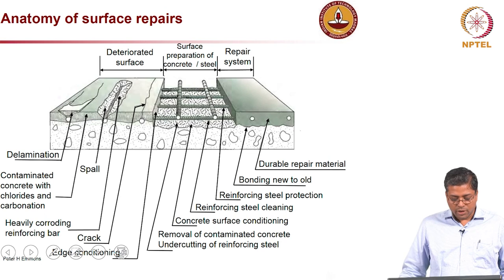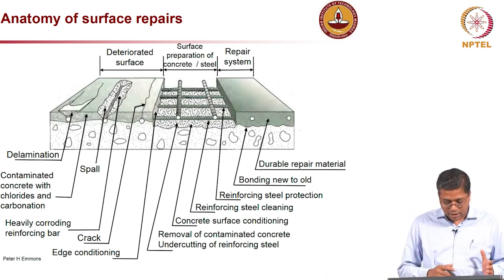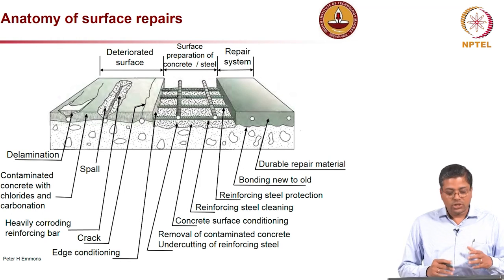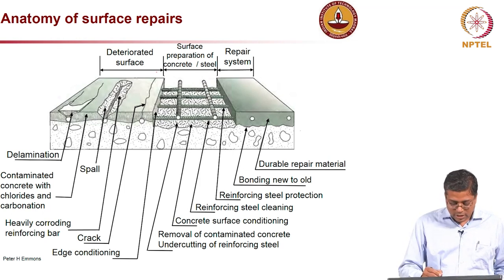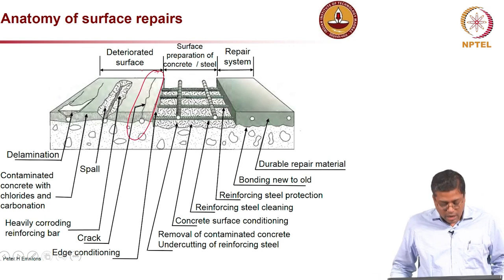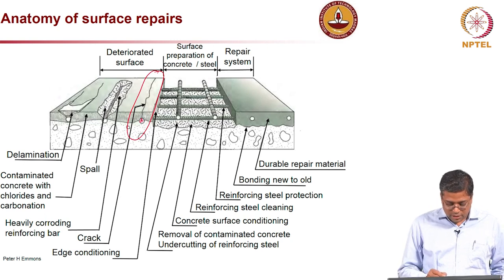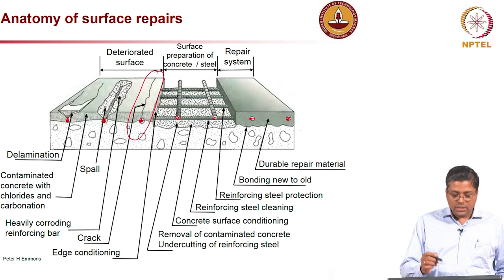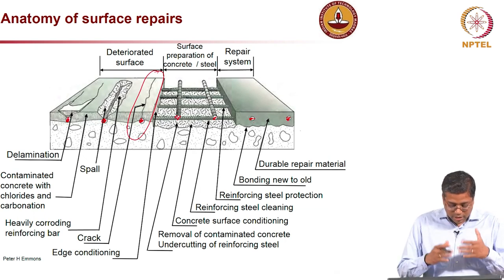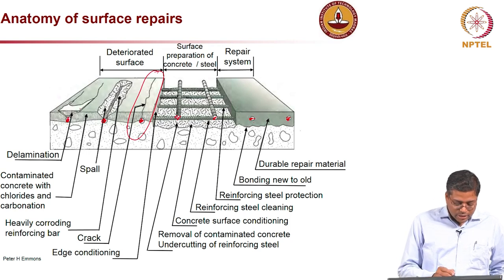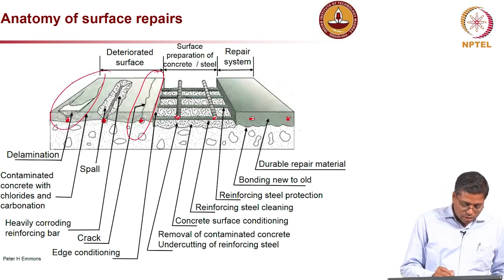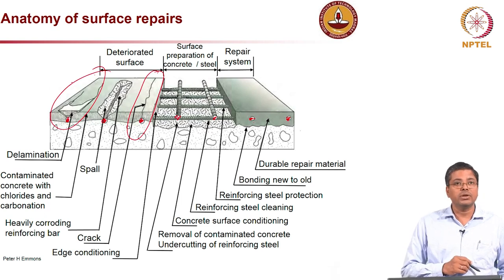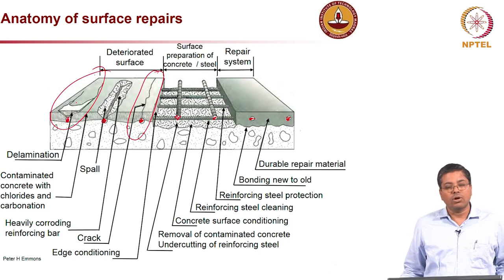Now, anatomy of surface repair. How is this happening? This is a nice sketch which shows what happens. In reinforced concrete structures, first you will observe some cracks happening. You can see here these are the rebars 1, 2, 3. Initially, if there is a slight corrosion happening, then there will be some cracks, and then this crack will further grow, or the corrosion will further progress, which will lead to delamination of the concrete,